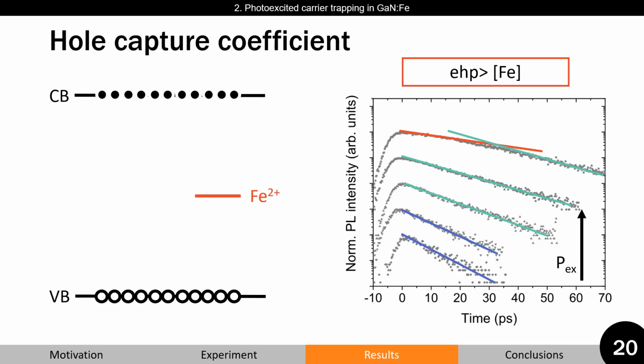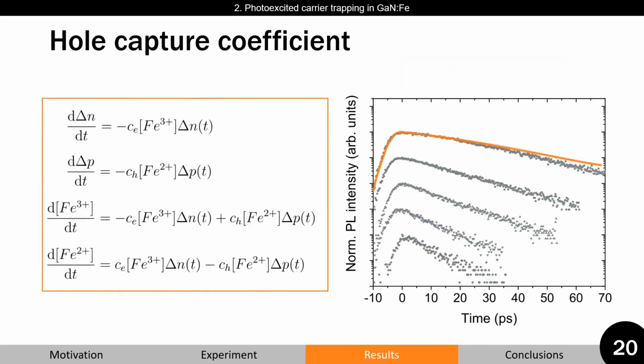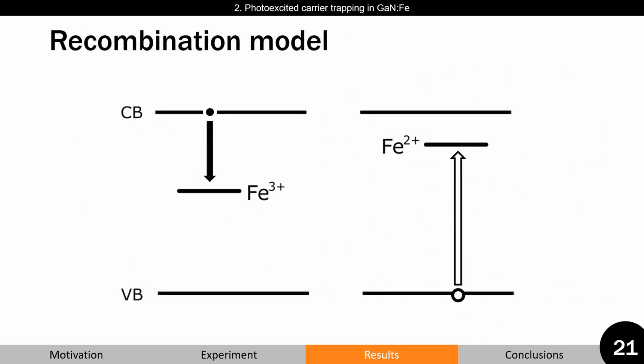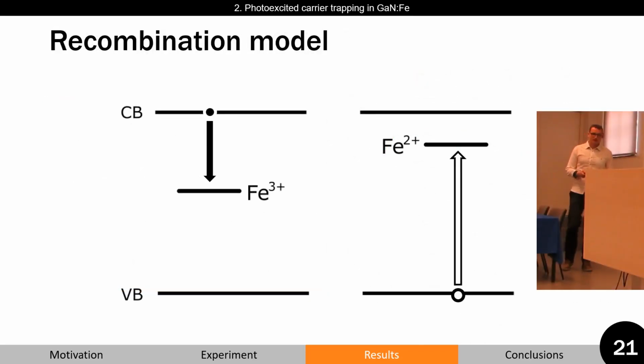This allows us to describe the system using a system of rate equations. We already evaluated the electron capture coefficient. Then, having a single unknown value, we can determine the hole capture coefficient. After determining these coefficients, two problems emerge. First of all, our electron capture coefficient is much larger than reported by other groups using different experimental setups.